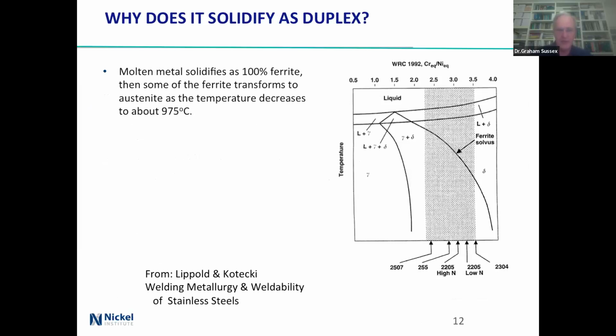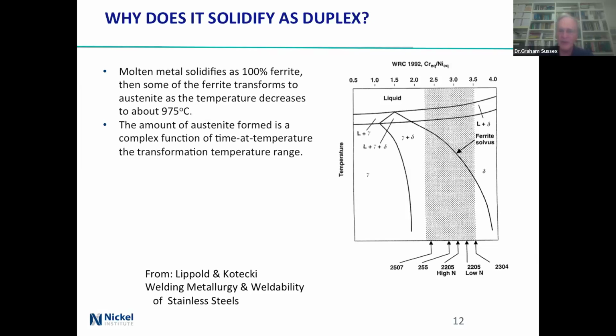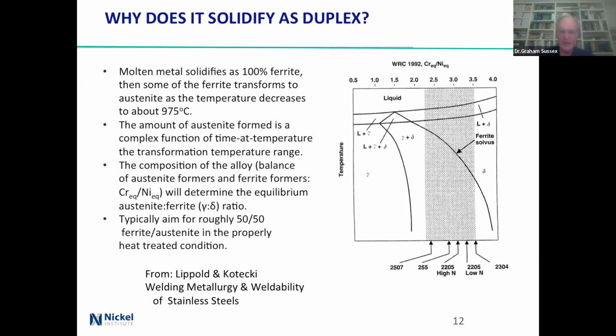So why does it solidify as duplex? This is a diagram out of Lippold on welding metallurgy and weldability. Good book, but it's quite heavy reading. The band down the center is where the duplexes are. The numbers across the bottom are typical alloys going across there. The metal solidifies as 100% ferrite, and then some of it's going to transform once it gets below about 975C, as it says there. It's a bit more complicated than that, and the actual number will depend on where you are across that band. Typically, you're aiming for about 50-50 ferrite austenite, but you can go quite a bit different and still get quite good results.